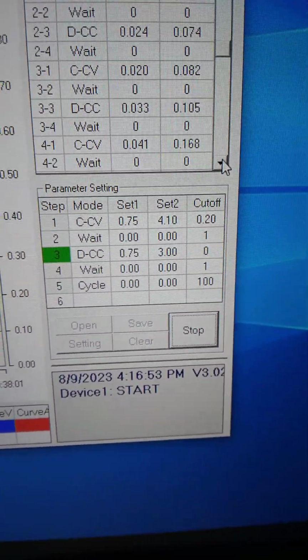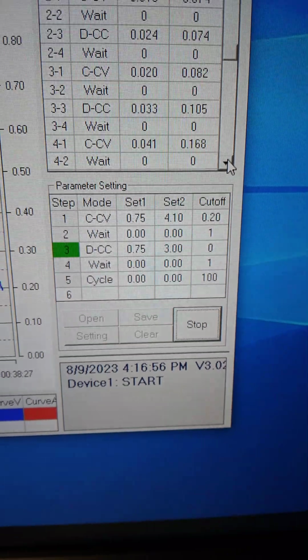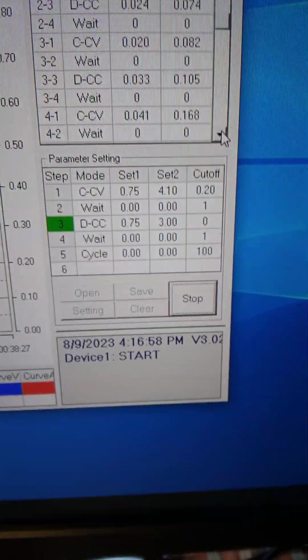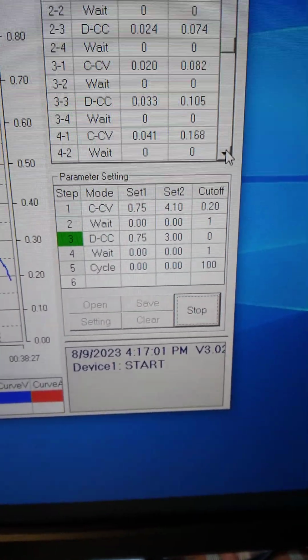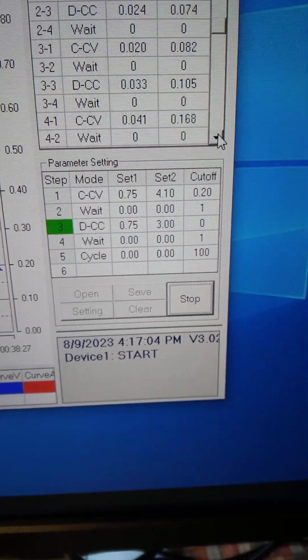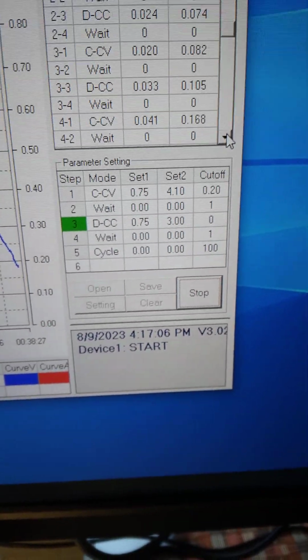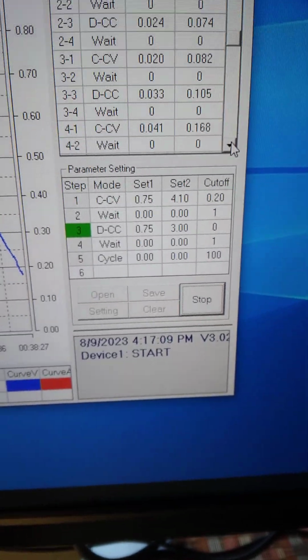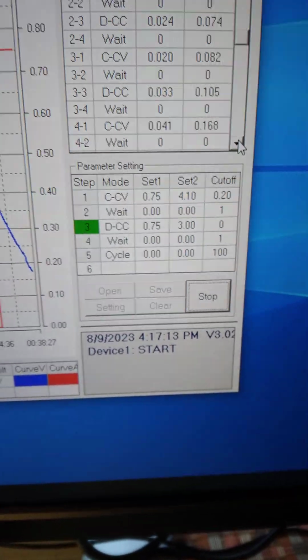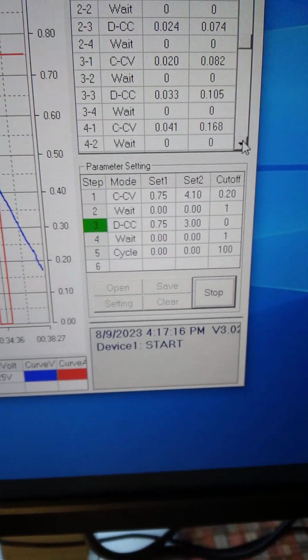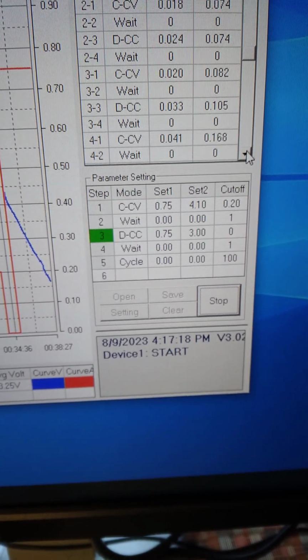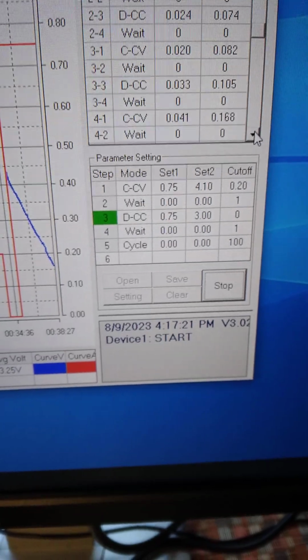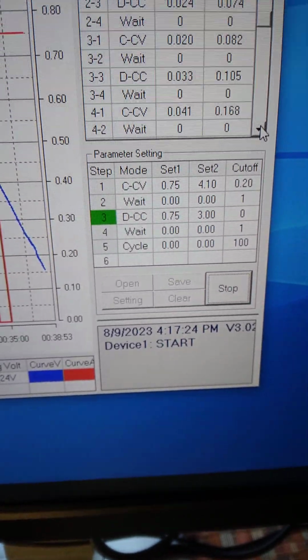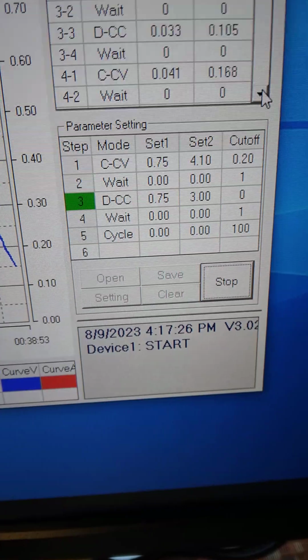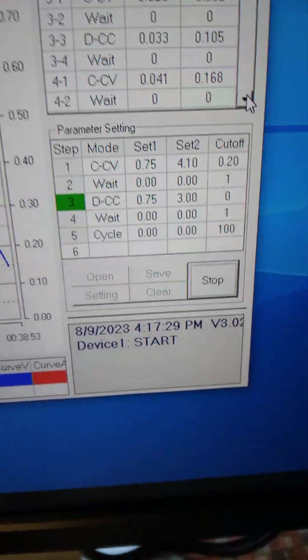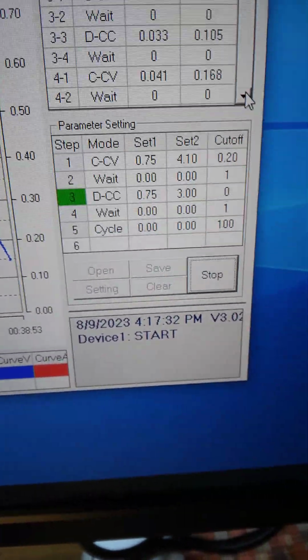And then we top it off with a constant voltage down to a cutoff current of 0.20 amps. Standard CCV conditions, but we're going up to 4.1 volts. Then we give it a rest period of a minute. Then we discharge, and we're using 750 milliamps for charging and discharging, and a cutoff for the lithium ion, we're using 3.00 volts. A rest period of a minute, and then the cycle continues.